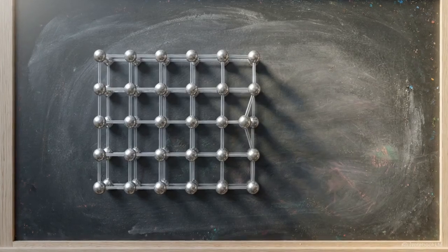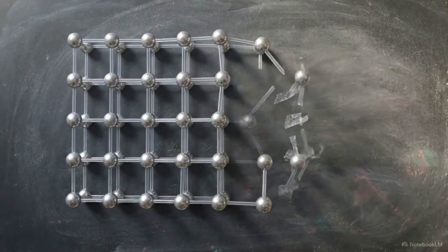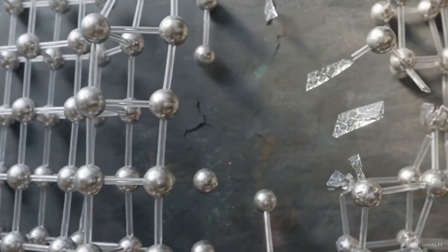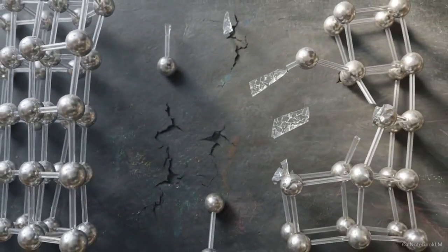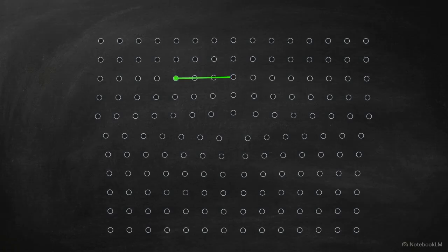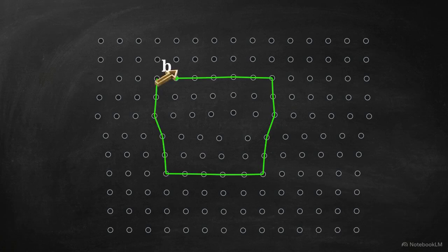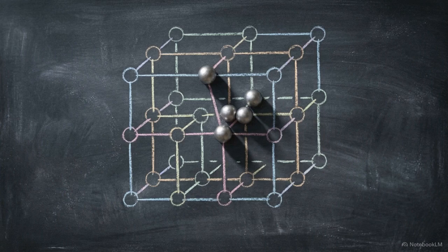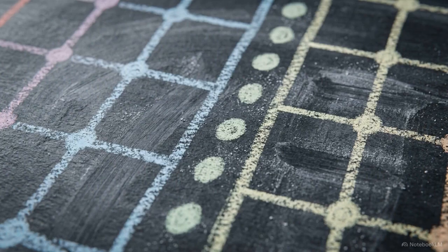If you draw a closed circuit of atomic steps in a perfect crystal, and then draw that exact same sequence around a structural defect, the loop fails to close. That directed closure failure is conventionally defined as the Burgers vector. This atomistic framing is highly effective for pedagogy. It provides a diagrammatic way to introduce basic plasticity and visualize how local atomic order survives even when the broader